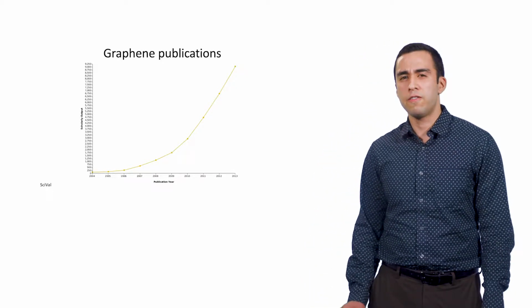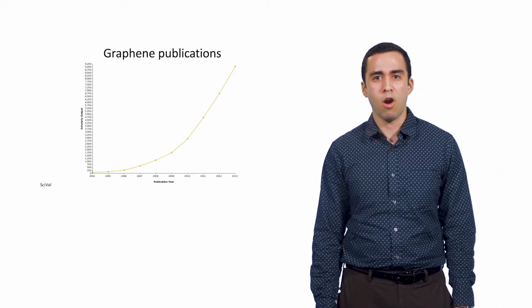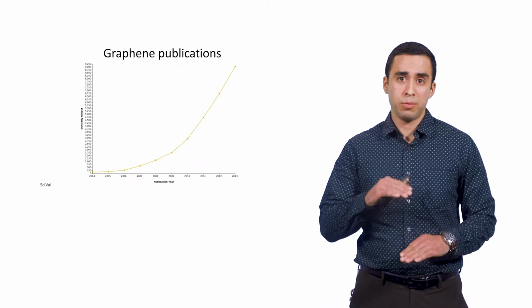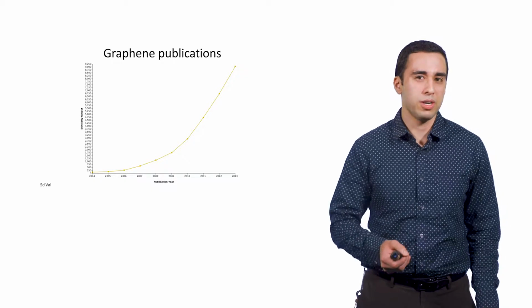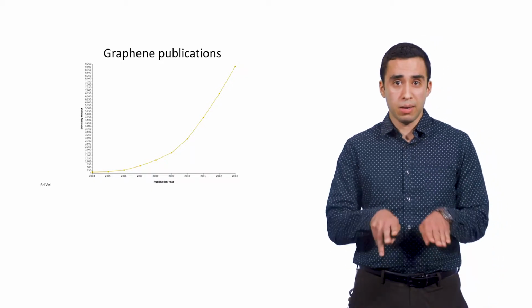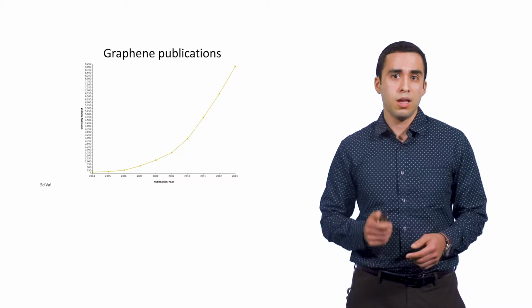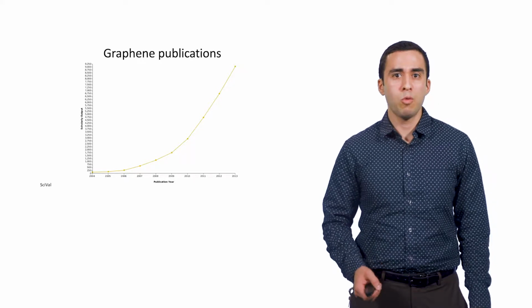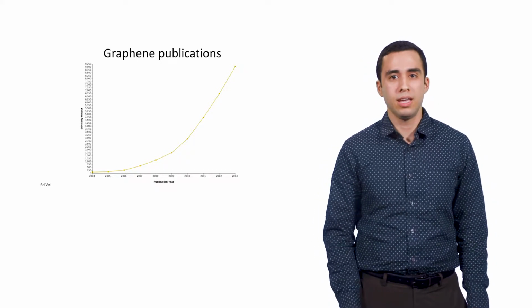Now, graphene is a fickle material. It must be made of a single extended sheet of carbon in order to have its core properties. If the sheets get stacked, like paper in a printer, it becomes more like the graphite in your pencils. Kind of boring. If you lay 2 papers side by side, the edges make it tricky to get a perfect continuous sheet. Graphene acts the same way. Its electrical and mechanical properties become worse when more flakes are added, which is how graphene oxide materials are made.